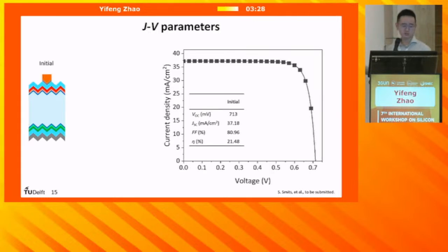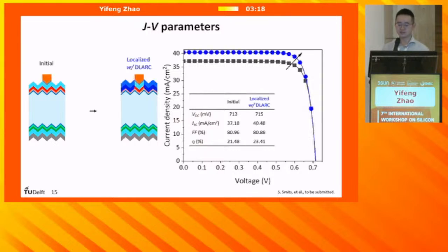We start with a conventional heterojunction solar cell, with full area TCO and full area silicon layers, and the JV parameters and the JV curve are given here. With the same cell, we processed this initial cell by the localization process we introduced before, and by adding an extra double layer anti-reflection coating, we can see a significant boost of the JSC, and most importantly, without compromising any VOC and fill factor.